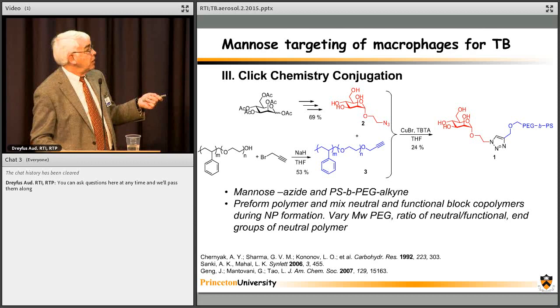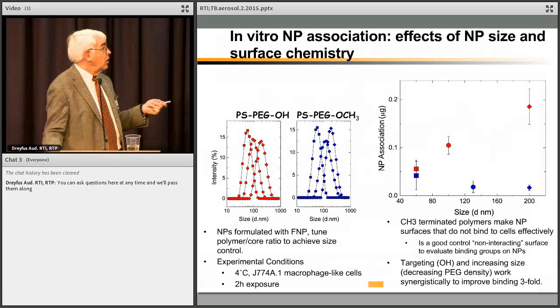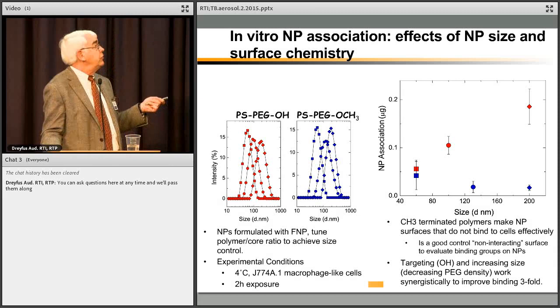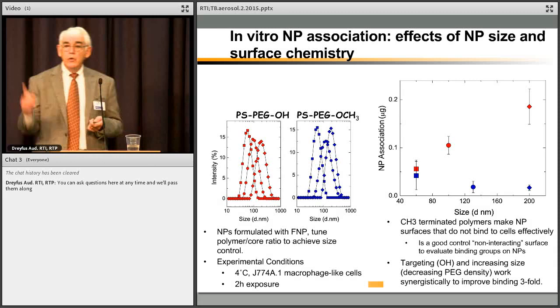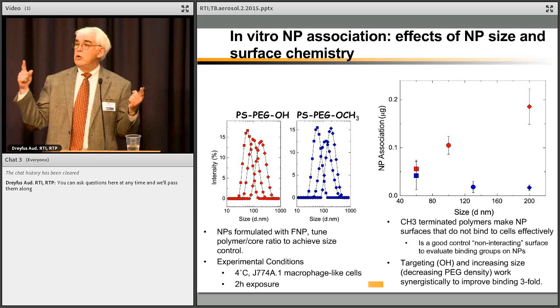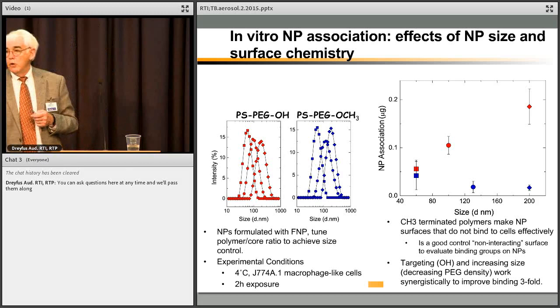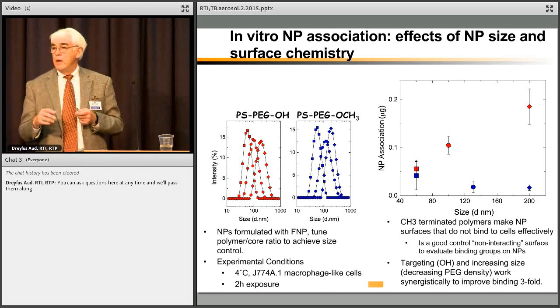We make a series of particles, we can change particle size by changing the core in this case, so we make these series of particle sizes very rapidly. What's interesting here is this is a hydroxyl-terminated PEG and this is a methoxy-terminated PEG. In the polymer science world, you say one group out of 104, so 5K PEG is 104 units, can't make much difference. It turns out it makes an enormous difference. It was actually Jeff Hubbell, I heard him give a talk several years ago, who pointed this out in terms of the uptake by macrophages in lymphatic drainage. And he found this big difference between PEG chains with OH versus PEG with methoxy.